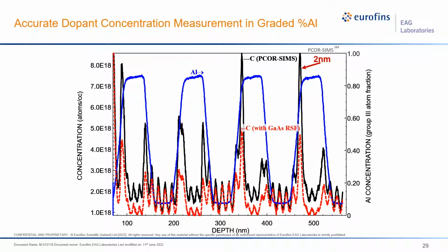This slide shows how carbon is present in large spikes at the interfaces between the high and low refractive index layers and in smaller spikes within each layer. The larger spikes are intentionally added doping spikes. The smaller spikes will be discussed in the next slide.